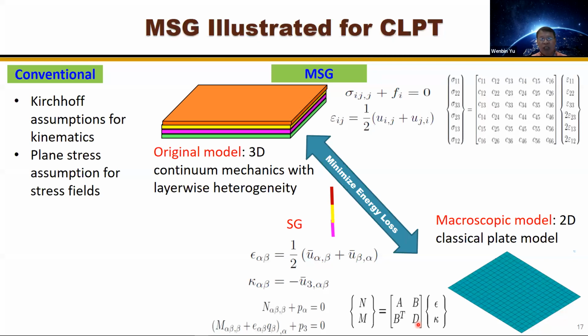plate stiffness. Traditionally, we take the Kirchhoff assumption for kinematics, basically generating a plane strain situation. Then we do a plane stress assumption. Instead of using C, we use Q, right? Sigma_ij equals Q_ijkl epsilon_kl. But we do know that plane stress and plane strain cannot exist at the same time. That's a contradiction. For this method, we don't have to make that assumption. We just need to minimize the loss of energy between these two models.